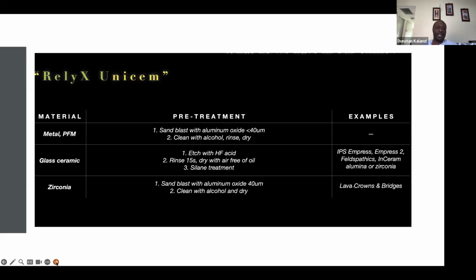If you're doing a metal PFM, you have to sandblast, and then you can use zinc phosphate or polycarboxylate, or you can use any of the dual cure or self-adhesive cements. For the glass ceramic, you treat, but you can use this RelyX Unicem. Even the same applies with zirconia. So if I was looking for a cement that might work across all my needs, I might be interested in RelyX Unicem.